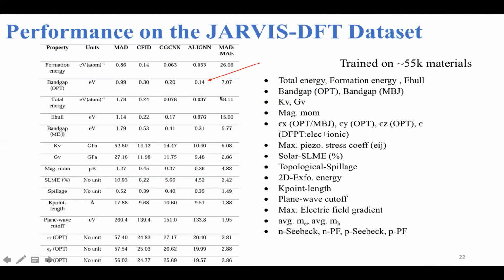We also tried this on the JARVIS-DFT dataset, which has 55,000 materials, around 14,000 materials less. We see that the formation energy MAE is higher, again because we have around 14K fewer materials. But interestingly, our band gap MAE is 0.14 versus 0.2 in the previous slide. This can be due to the different density functional method used, or there can be several reasons, such as different convergence criteria and so on.